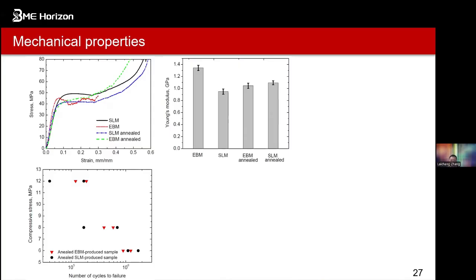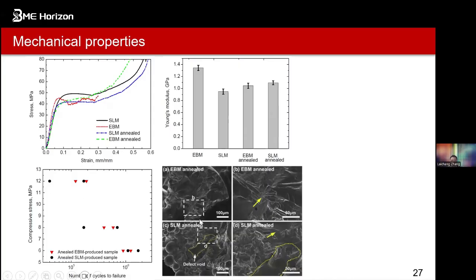However, at the high stress level, crack initiation and propagation from the pores tend to occur. Therefore the SLM samples, which contain a high number of defects, as we showed on the last slides, have a lower and more variable fatigue life. You can see the gap is much bigger. Of course, we can show here some samples that also have fatigue striations. You can see there are a lot visible in most crack regions of both EBM and SLM parts.